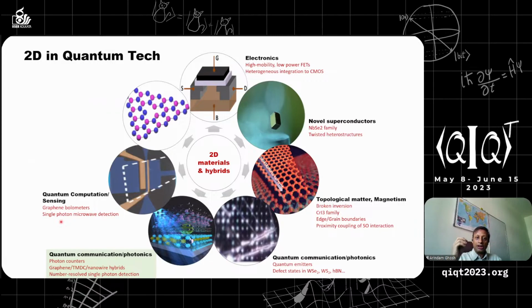You can measure single microwave photons. It's still at about 30 megahertz, slightly high. Now the noise in such devices is continuously coming down. Because graphene and two-dimensional materials are just one layer, you can use them as wonderful bolometers, because a tiny amount of heat can change the temperature very much, and you can detect it through their electrical properties. So this is a key advantage of two-dimensional materials, because of their low mass and specific heat. And also quantum sensing with spin defects in boron nitride and magnetic sensing are directions that are coming up very, very rapidly.